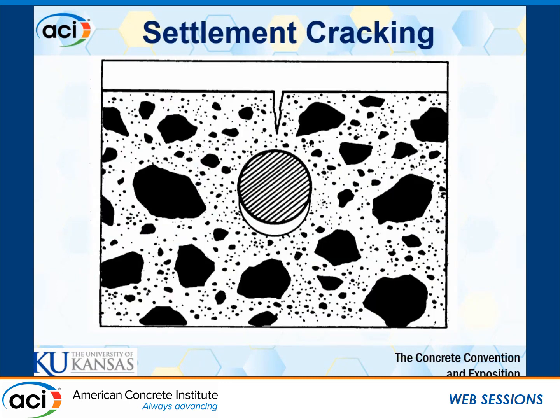So settlement cracking. Mechanism for that, if we visualize just a section of concrete there with our reinforcing bar in the middle, those rebars are in there as kind of a restraint. And when we pour fresh concrete over the top of that, that concrete's going to want to flow over the surface of that rebar. The solids in there, aggregates, are going to want to subside to the bottom, and the water and cement paste is going to want to rise to the top. And in more extreme cases, what causes those cracks is you can have localized tensile stresses shortly after that concrete begins to set and harden and leave you with a settlement crack.